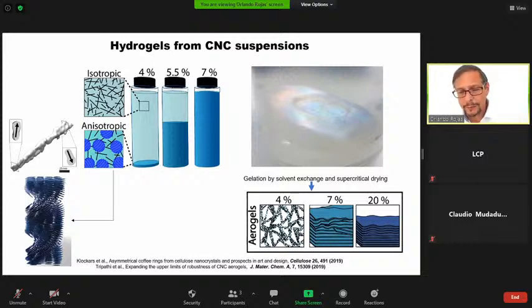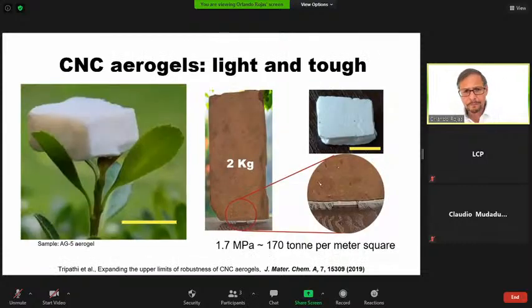And if we take that material in the bottom and we remove water by drying techniques, then we get a hydrogel that then eventually can be converted into aerogel by removal of water. But the beauty of this type of hydrogels and aerogels is that they keep the chiral nematic structure of the nanocrystals. And for that reason, you see on the top that there is some light reflection that is very interesting. And that light reflection speaks to something that I will show next, and this is the optomechanical response of the material. But before going there, I want to say that because of the structuring of the nanomaterial, these very foam-like three-dimensional objects, these aerogels, are capable of supporting very high weight. So here you have a brick, 2 kilograms on a very small area. That can be scaled to 170 tons per square meter of resistance of these very lightweight aerogels.